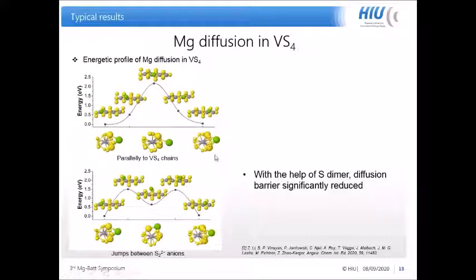Or have they been obtained differently? Sorry, are these DFT results? Yes, these are DFT. Okay. Yeah, because this is kind of a controversy, because you have here barriers up to 2 eV, and if you compare it to the spinels, this is much lower. And nevertheless, it seems that the magnesium is migrating well in these chain-like structures. So it may be the way how it was calculated, from the colleagues at the DTU, right? Or who did it?